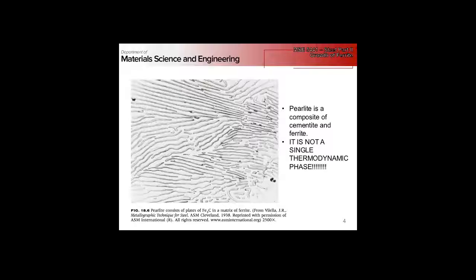Bunch of stress concentrations in specifically aligned plates. You're going to basically propagate a crack more easily, I'd imagine. So you're going to nucleate a crack more easily, right? There's aspects of both answers that are right, because here the crack is going to nucleate easily at the interface, right? But then you're going to break multiple laths, right? So you're going to be absorbing energy in short punctuated bursts between plastic deformation in the ferrite laths, right?